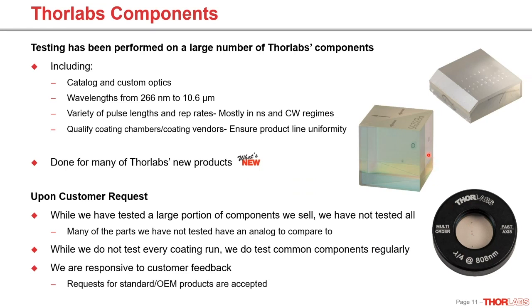So here we have a number of products that we've tested. This is a beam splitter cube. And if you look carefully, you can see this damaged spot that's on the cemented hypotenuse interface rather than one of the four exit faces. And that's because for this particular beam splitter cube, the lowest damage threshold surface is going to be that central interface because it's cemented. So many optical cements are obviously not quite as high power as the AR coatings. So we want to be sure that we're testing the part of the component most likely to fail. If, for example, this beam splitter cube fails at 5 joules per centimeter squared at the cemented interface, you're not going to care if the AR fails at 10.